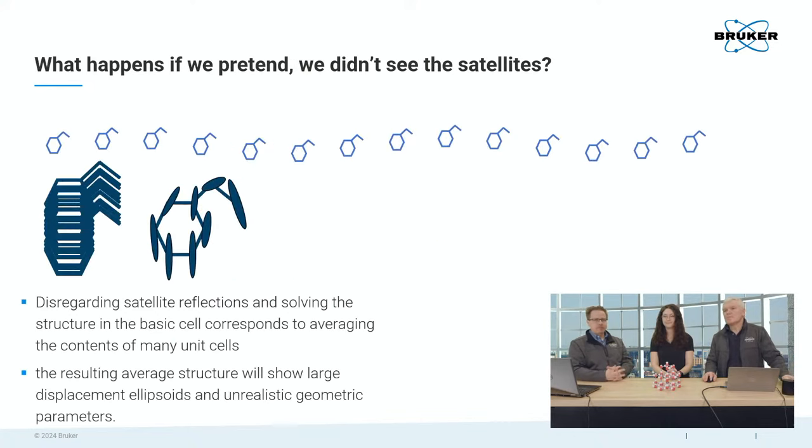Yeah. All right. So what happens if we pretend we didn't see those satellites? And this happens a lot. Filter them out, right? Yeah. Just get rid of them. Either you have older instrumentation, you don't see them, or sometimes the software is so good it will just index and then you don't see that. You get the idea now that you average all these positions, just push them all together, then this is what you get